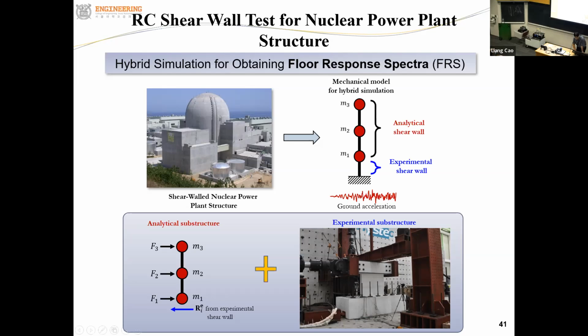That's the typical nuclear power plant structure. We modeled the shear wall system here using this structural model. The first story was tested in the lab using the test setup here, because when you have a strong earthquake, the damage will be concentrated in the first story. So the second and third stories will pretty much remain linear elastic. We modeled this part using the tri-linear model, and the first story shear wall is experimentally tested using this test setup.